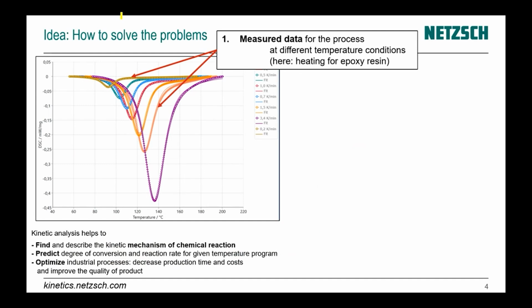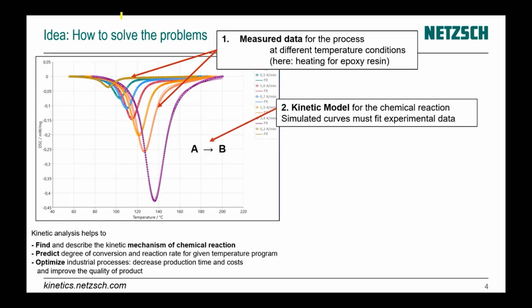The idea: firstly, we have laboratory measurements at different temperature conditions. For example, here is a DSC measurement at different heating rates. After that, we analyze this data and create one common kinetic model which can describe all this data for different temperature conditions. Here, for example, we have points which are our experimental data and a line which is our model. And we see that this model can describe all experimental data very well.